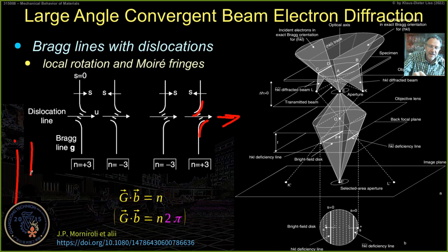You remember, a dislocation is something like that, where we have bent lattice planes. So around the dislocations they are a little reoriented, and this reorientation over Bragg diffraction magnifies to a large angle. Even if the angle is small, with Bragg diffraction you can magnify this reorientation angle to a large amount. So this is the bending qualitatively.